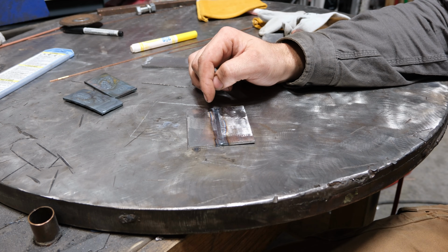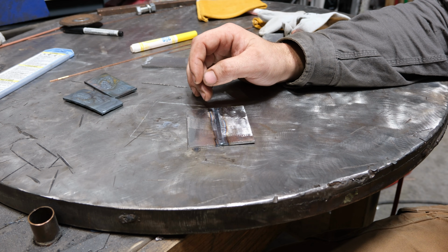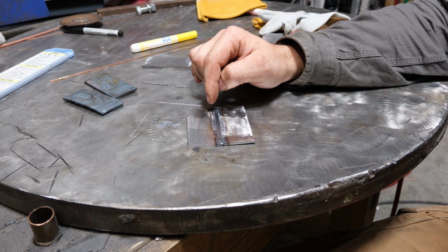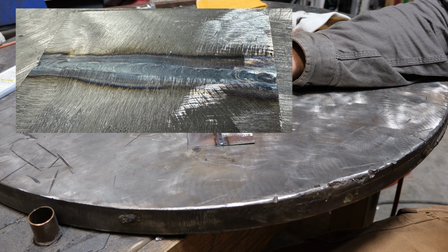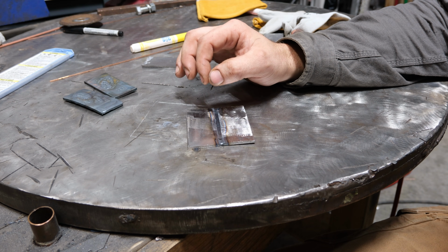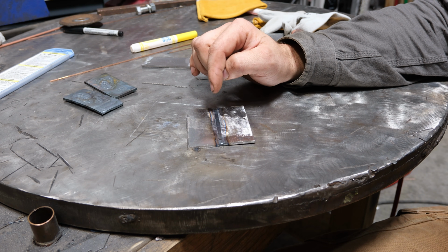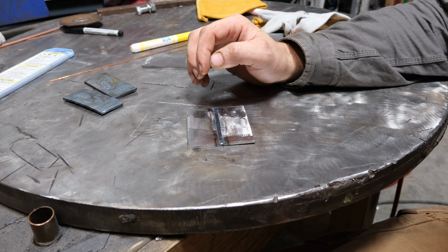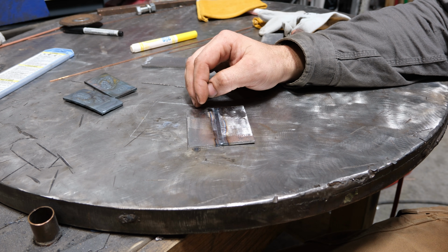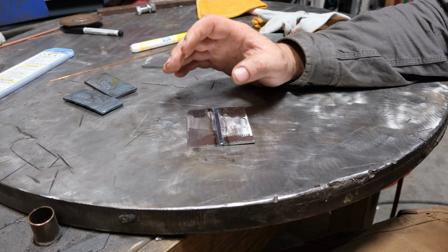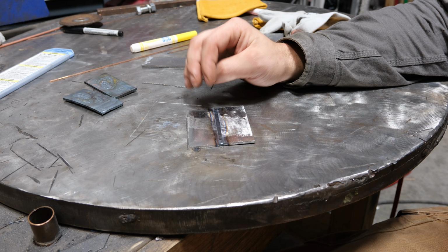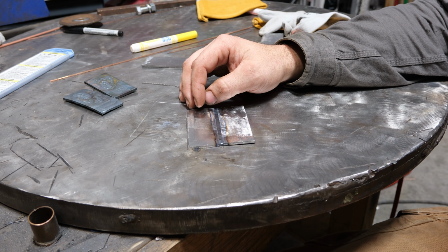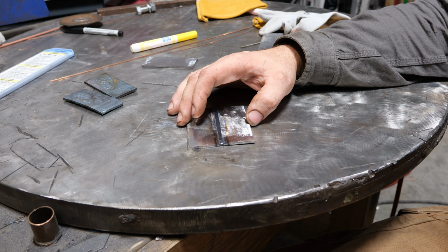Based on what we see here, one of the telltale signs that I was consistent as a welder is the fact that the heat affected zone lines that turn red and blue and purple are very consistent. Now, no, they're not a straight line, and my travel speed was a little bit inconsistent, but for the most part, they look very good. If you see very inconsistent heat affected zone lines, that's telling you that your travel speed, your arc gap, all of that is just not consistent. You want to see more or less a fairly straight line. That would be ideal. Now I'll put up another picture that we can look at.